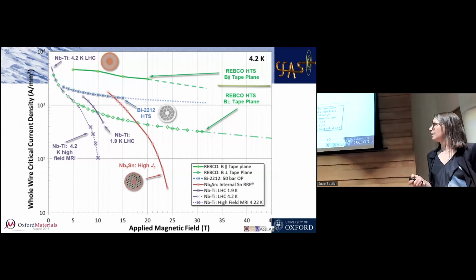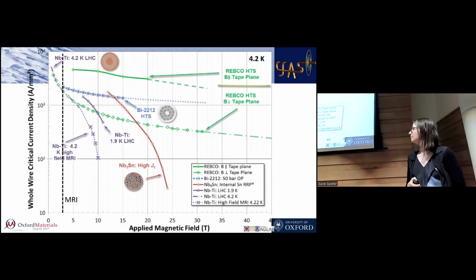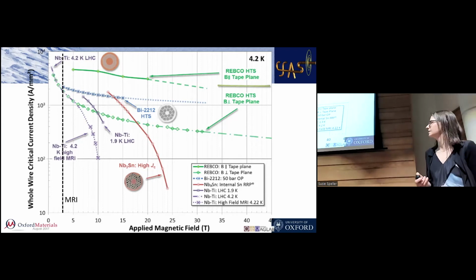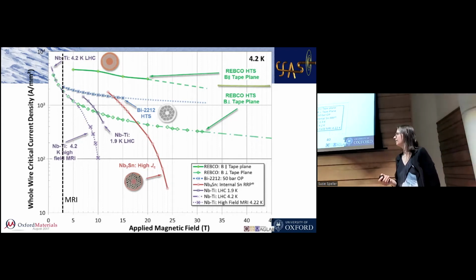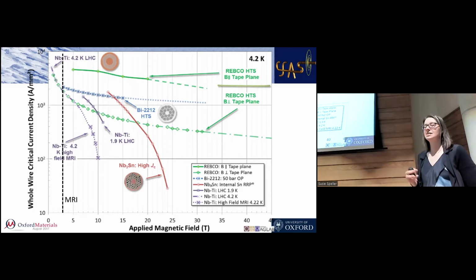Now, an MRI machine uses niobium titanium and it has a magnetic field of around 3 Tesla. Not all of them, some of them are lower than that, some are higher, but conventionally they're around that kind of amount. So niobium titanium is absolutely fine. One of the really strong permanent magnets that you can buy is about 1 Tesla. So that gives you some idea: a Tesla is a very big unit of magnetic field.